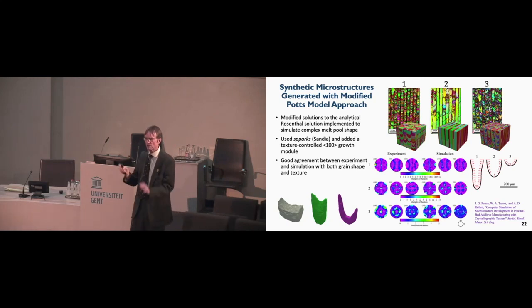And so big changes in shape, and if you recall that solidification tends to happen following the temperature gradient, then you can perhaps immediately see that the growth directions are really very different between those three different melt pool shapes. And you can see these bits of melt pool here. And so you go back to these microstructures and you ask, well, where are those long skinny grains? Those are the grains growing up the center of the melt pools.